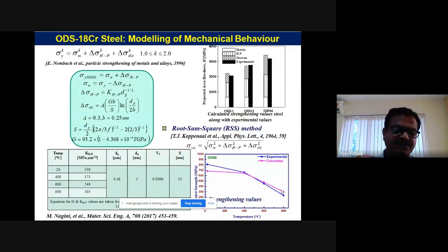Even at exposure to higher temperatures, these fine dispersoids which are available on the grain boundary or within the grain don't allow the grain to grow. So that's why this fine grain structure still gives you the strength at higher temperatures. So that's the beauty of these materials.